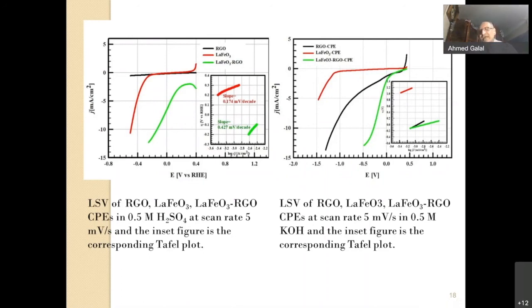Now, when we first tried to publish this work, the comment came from both reviewers: it will be okay if it is believed to be real. So we had the first rejection without any further comments, because it was not accepted to have such a shift beyond the zero potential for the onset of the hydrogen evolution. We have tried to confirm that there is no impurity present in the samples over the surface of the electrode, and to purify the electrolyte as much as we can. So we compared our results by running the experiments in sulfuric acid as well as in perchloric acid.